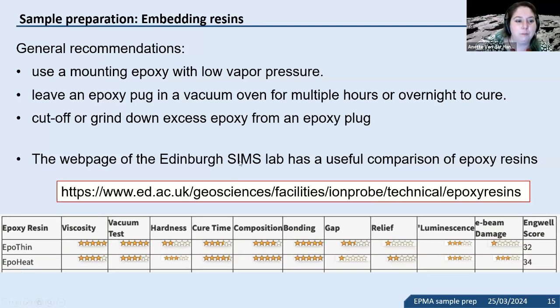Again, you can have a certain thickness, but you don't want to have an inch or something of just epoxy. And this webpage is just fantastic with a lot of common resins. Here's some example, and they looked at viscosity and the goodness of vacuum that you get and the cure time and hardness and the gap and whatnot. And it can be very good to guide you what epoxy to get.